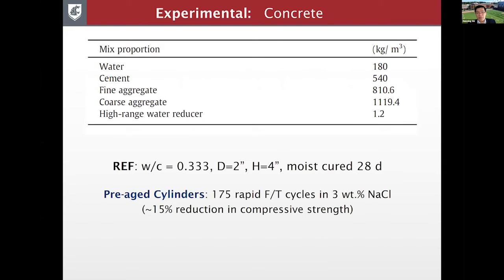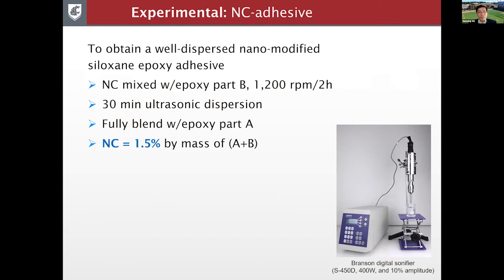So here's the mix design. As you can see, the water cement ratio of this concrete is 0.33, and it's a 2x4 inch small cylinders cured in the lab. And then the pre-aging was done through exposure to 175 rapid freeze-thaw cycles in 3% sodium chloride. And we are achieving approximately 15% reduction in compressive strength. And then we call that a different group, which is a pre-aged concrete group. So for dispersion, again, we're looking at about 1.5% by weight of the final epoxy adhesive and using ultrasonic dispersion.